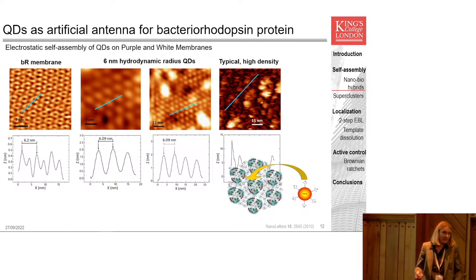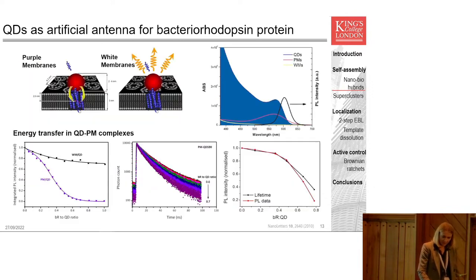However, in a general case, the steric interactions between quantum dots between each of these units will prevent them from depositing nicely, and so you end up with a more or less disordered organization of quantum dots. Nonetheless, there were cases where we were able to assemble the system very nicely without going to the full chemical conjugation route, which we also did do. But even with the self-assembled systems, you can again see a very nice transfer of energy, and we can see that both in the lifetime quenching and in the fluorescence quenching for the quantum dots.